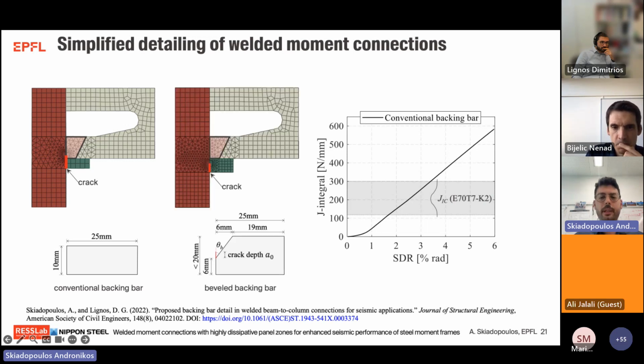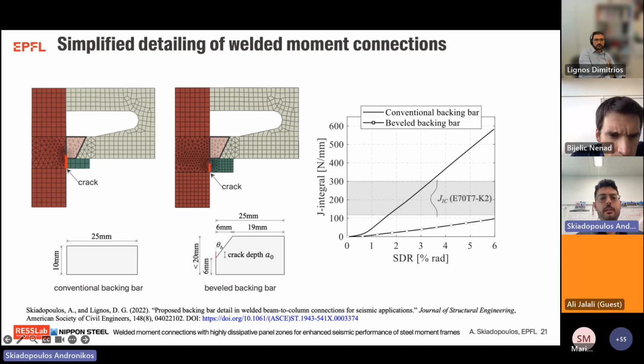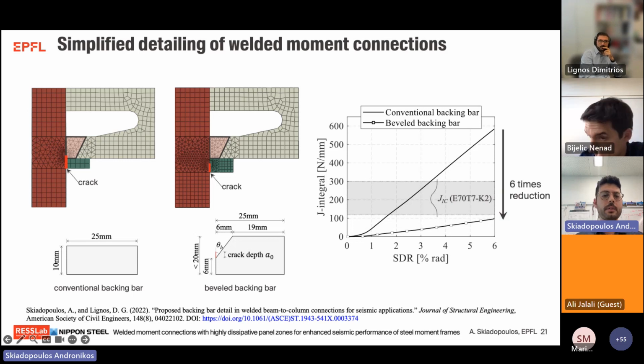Motivated by this, we came up with a bevel backing bar geometry that basically keeps any potential crack away from the critical beam flange region. The fracture demands from our proposed backing bar detailing are compared with the conventional backing bar detailing, and what we see is that the fracture potential is reduced by more than 6 times, and fracture in the beam to column connection is not expected even at 6% lateral drift demands. These conclusions were also confirmed by a series of parametric analyses that are not shown here in this talk due to brevity.